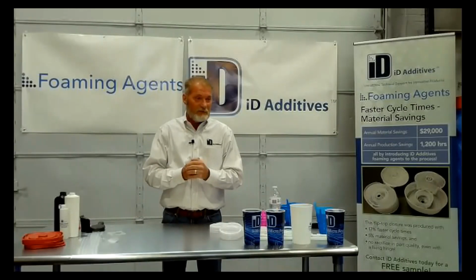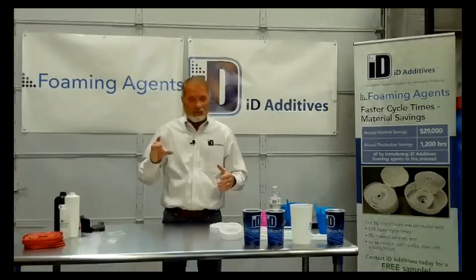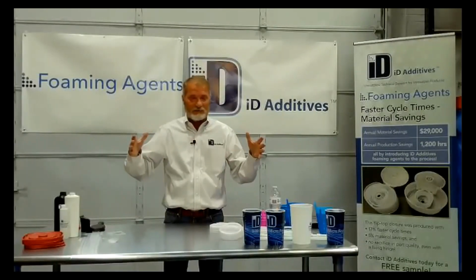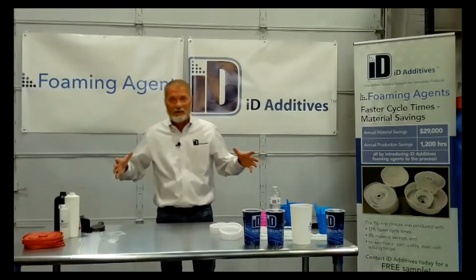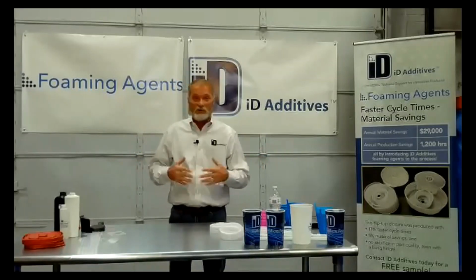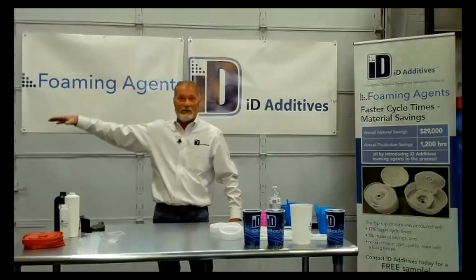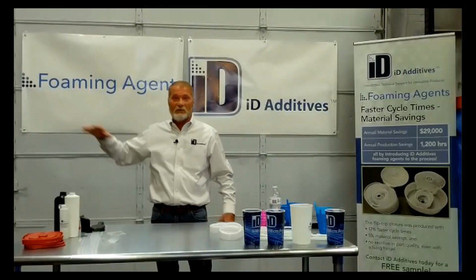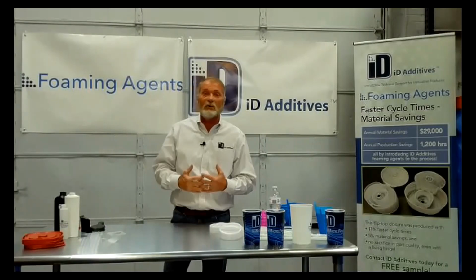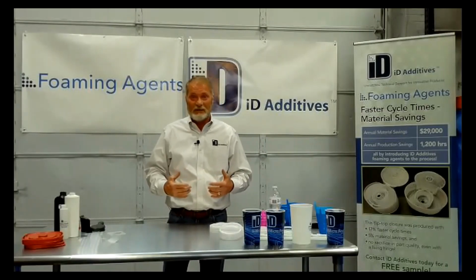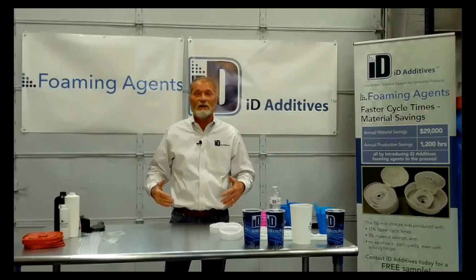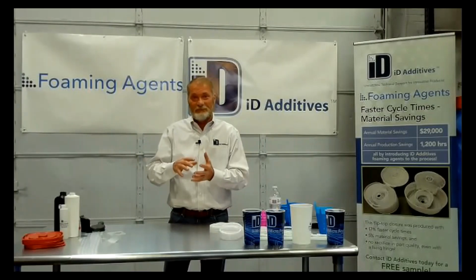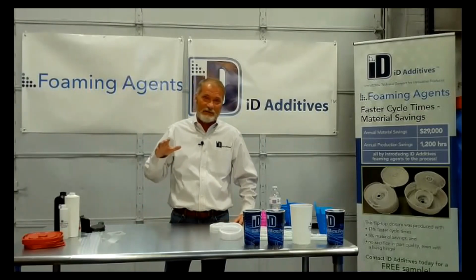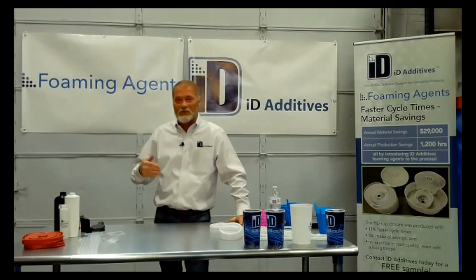Because if you try to run it too fast, or if you're pushing a bunch of nitrogen in there and you've got a fairly long cycle and the parts come out looking great, you may run into something we call post-blow, which means you can put them on a truck, take them down to Florida, set for a week, and they start pulling them off, and they got blisters all over them. That's what I call post-blow. What I call blister is when it comes right out of the mold, and you got blisters on them. And that's all nitrogen. So if you can get the nitrogen down, it means you can run faster without blister and without post-blow.